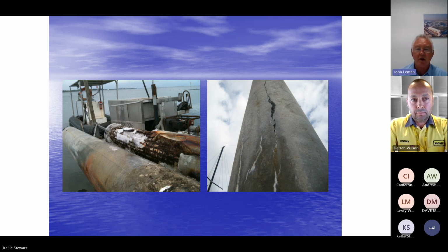You can see on the right there are the beginnings of corrosion, because typically these piles are designed for a 25-year design life. There's a lot of stuff around that's a lot older than 25 years, and you can see there it's getting towards spalling the concrete right off it. They have tried to do repairs with these piles, but the chloride has really got right in and behind the reinforcement. So even though you can scabble it all off and epoxy repair it, it usually blows the repair off over a short period of time.